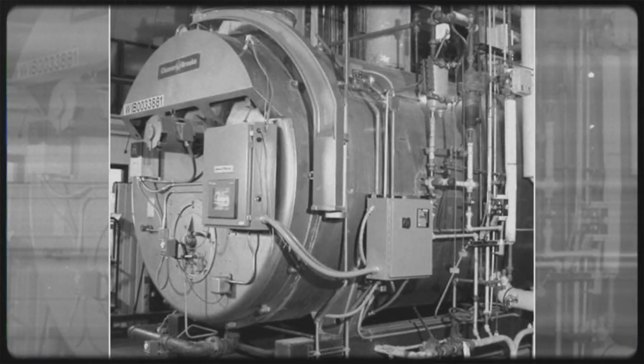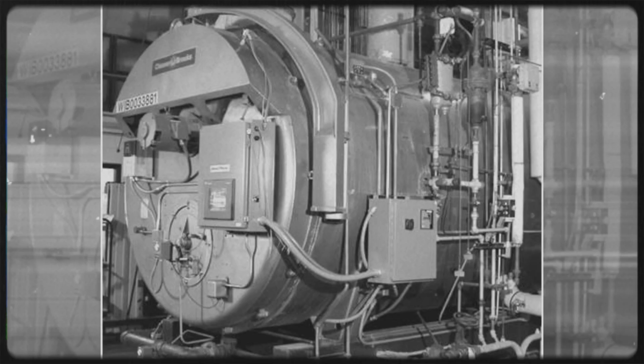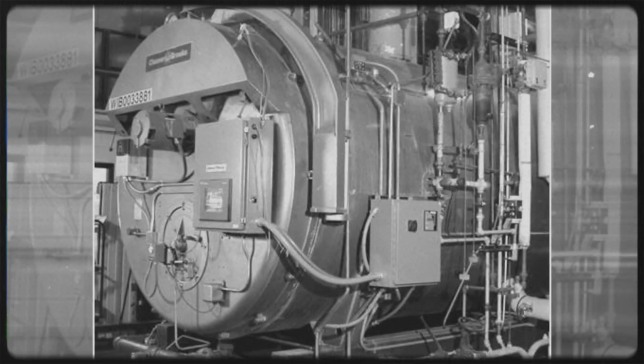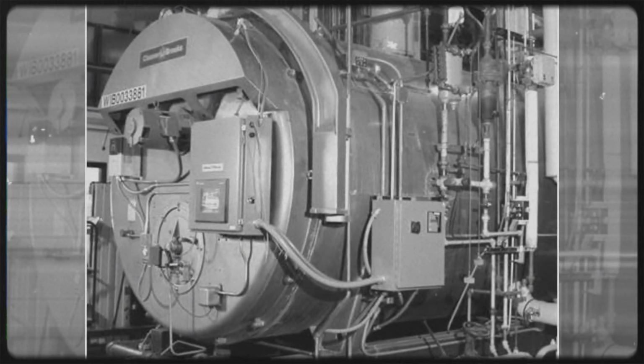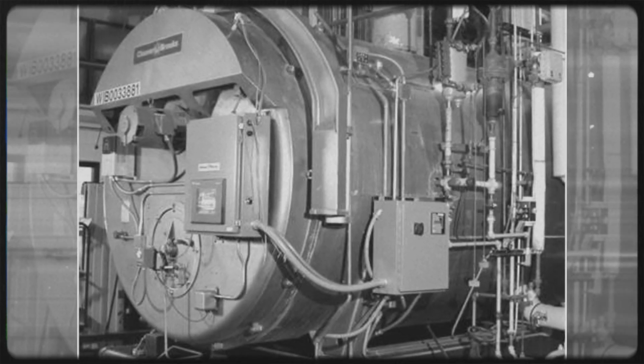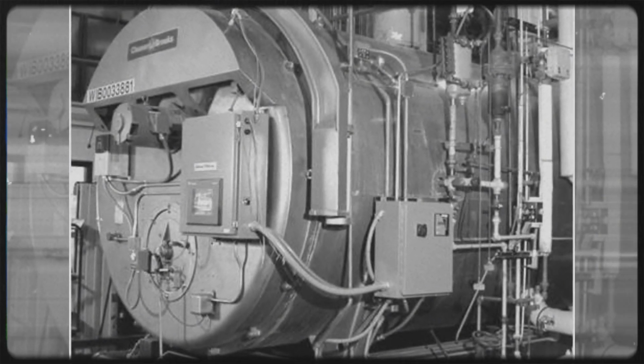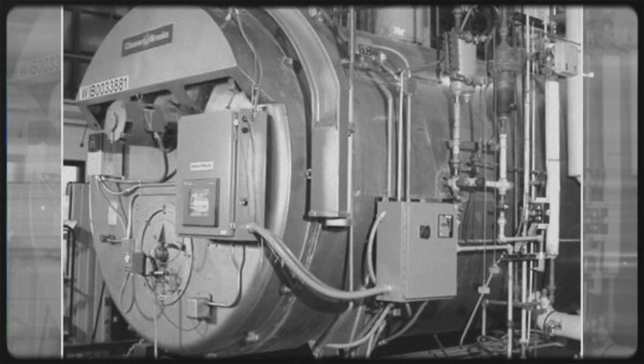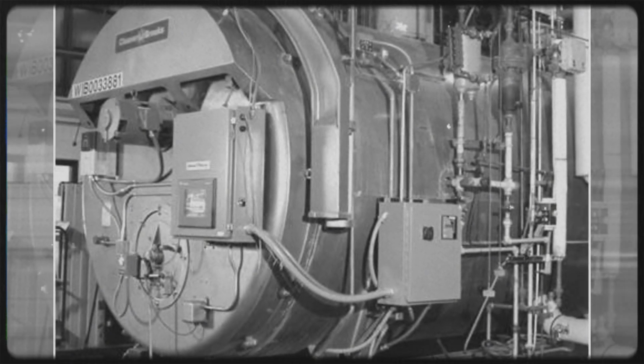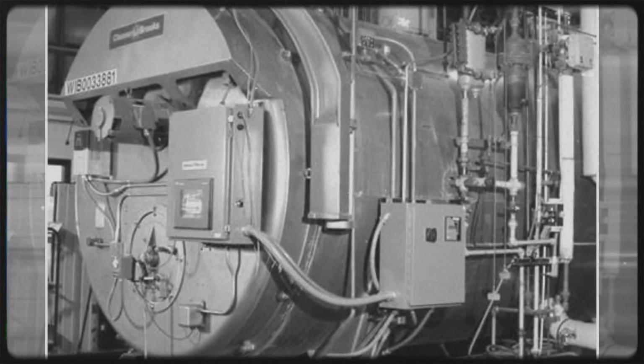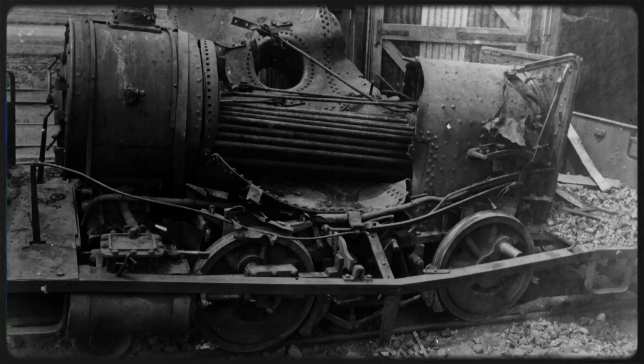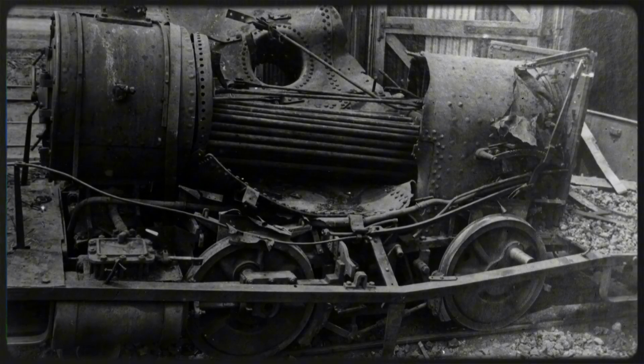The physics of scale and corrosion interact with these explosion dynamics in interesting ways. Scale does not just cause local overheating, it changes the heat transfer dynamics of the entire boiler system. A heavily scaled boiler requires more fuel to produce the same amount of steam because the scale is insulating the water from the heat. Operators who noticed that their boiler was becoming less efficient often responded by increasing the fire rate, putting in more fuel, running hotter, which meant that the already weakened metal behind the scale was being subjected to even higher temperatures. It was a feedback loop that could accelerate toward failure.